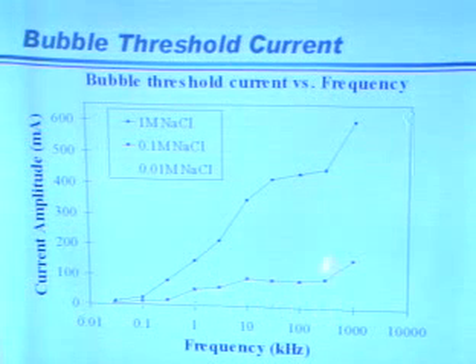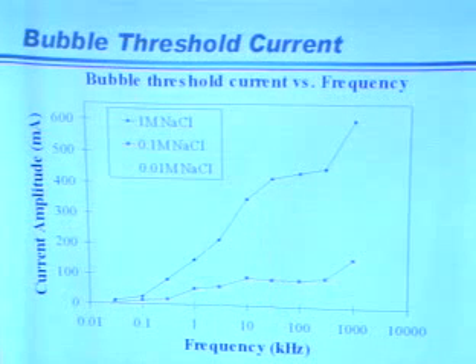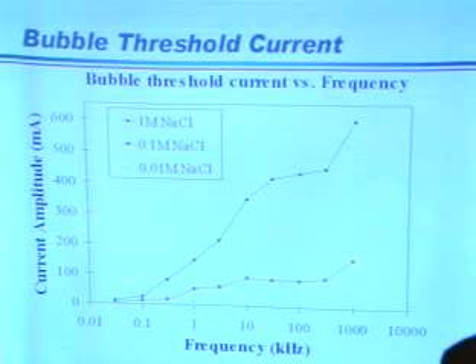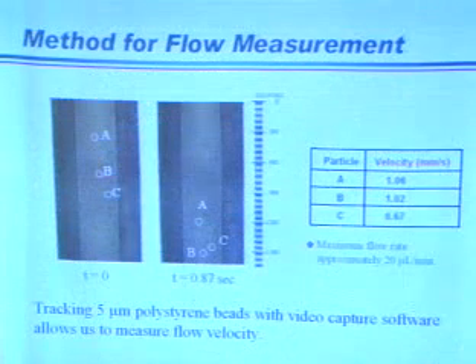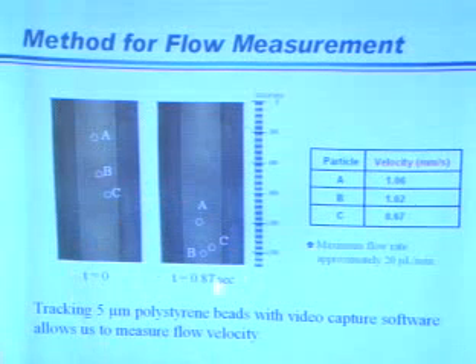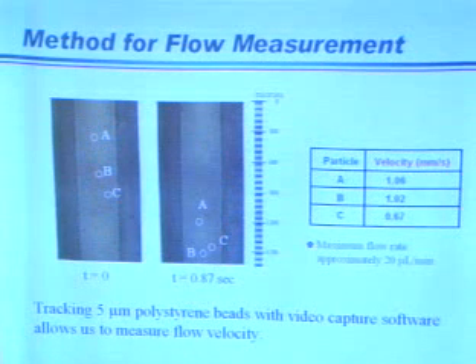And the higher the frequency allows you to get higher current amplitude, which is important to give enough head or pumping force. And then the higher concentration gives you more ions to work with, so you generate more force. And we use basically the image capturing technique to judge the flow speed and therefore derive the flow rate.